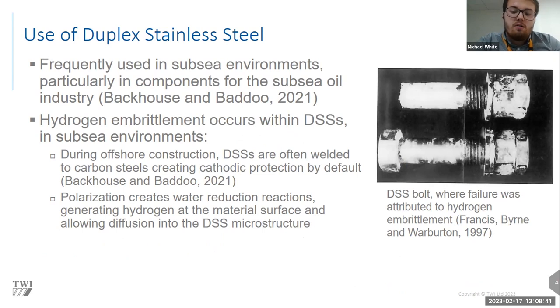Duplex stainless steels during construction are often welded to carbon steels, which inherently results in the occurrence of cathodic protection. The cathodic protection which occurs creates hydrogen through reduction reactions at the surface of the metal, which then permeates into and diffuses through the duplex stainless steels. This very much shows that cathodic protection is not a very good method for preventing hydrogen embrittlement, and in fact causes it and makes it significantly worse, which brings me on to talking about hydrogen embrittlement and diffusion of hydrogen within duplex stainless steels.